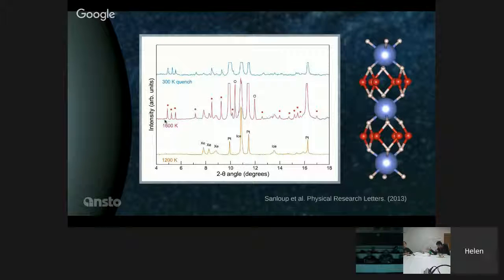But then you can see as we warmed up, we got to 1,600 Kelvin, so pretty hot on the laser. And there was a bit of a change. And you can see we got these brand new peaks arriving here. So these ones I've symbolized in the red there. And we actually got two new peaks of material. So here's still the platinum. This other material is new.